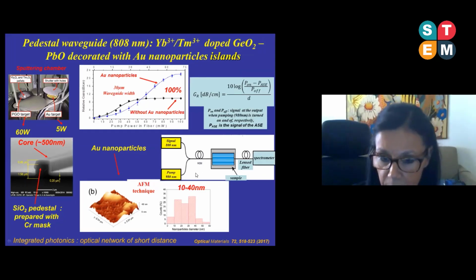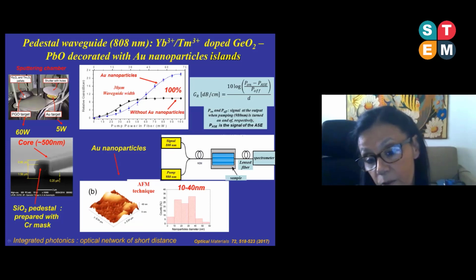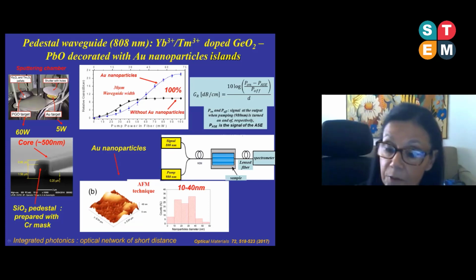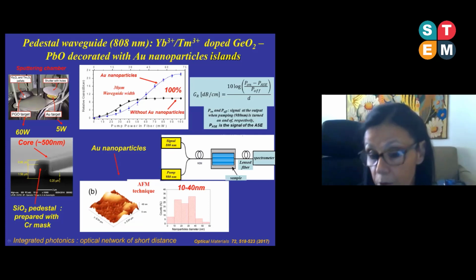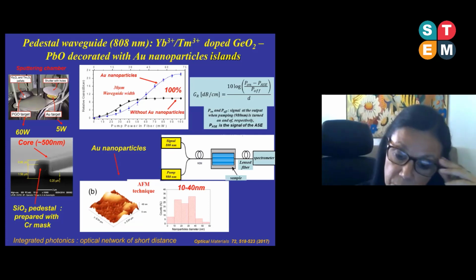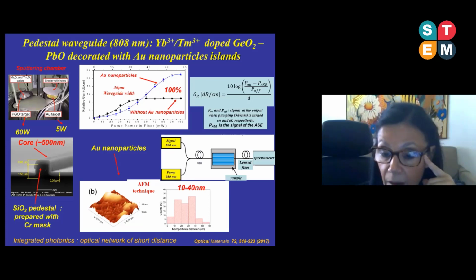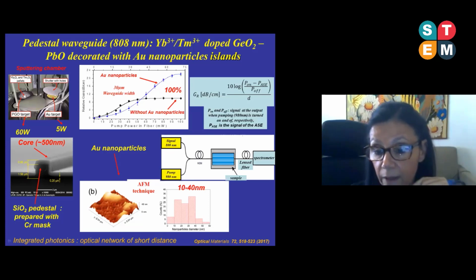And this figure illustrates the experimental setup used to determine this relative gain, where signal and pump are multiplexed by a WDM, sent to the sample, and the signal is collected from the sample by a lensed fiber, a lens especially produced for this experiment with 1 micrometer diameter, and the signal is finally sent to the spectrometer.